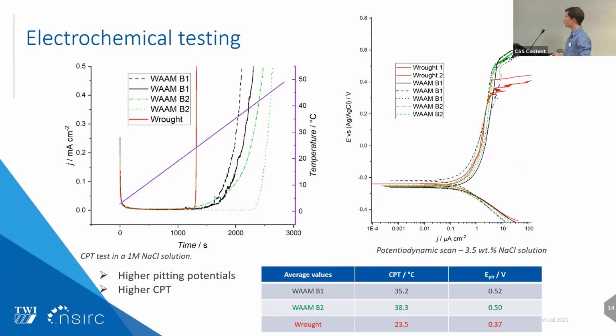We also performed critical pitting temperature testing, which is also a test used in the industry to qualify the corrosion resistance of an alloy. Here you can see the curves of the current density against time. As the time increases, temperature increases, which is a standard critical pitting test. At the moment we create pitting, we know the temperature, and that gives us the critical pitting temperature.